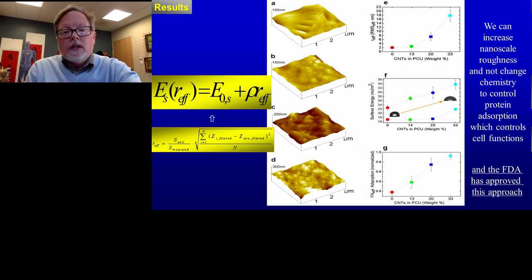And that's exactly what's shown on this slide, going from A, the smooth polycarbonate urethane, to B, which has a little bit, a couple more nanoscale features, going to C, which has a lot more nanoscale features, and then to D, which has the most nanoscale features. We created nanoscale features here by putting carbon nanotubes underneath the polymer. Carbon nanotubes are nanoscale orientations of carbon, and that provides this type of roughness. The more we add, the more roughness we get.